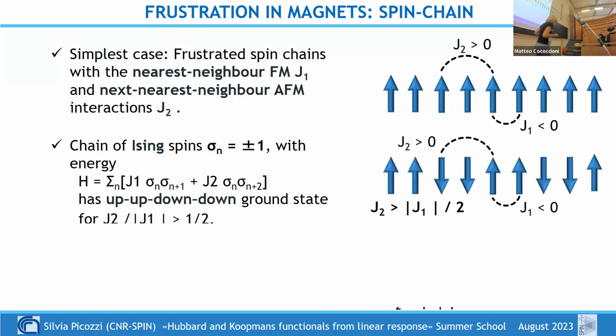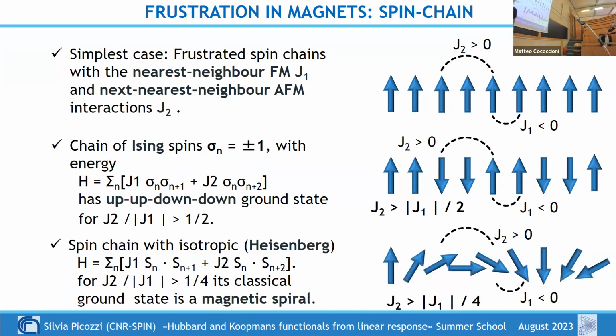If you have strong anisotropy, the spin-orbit is strong and tries to align your spins along a certain direction, then the ground state is a spin chain which is like up, up, down, down. So at least the second nearest neighbor interaction is always satisfied. If your anisotropy is not that large, then you have a helix or a spin spiral, not necessarily a helix.